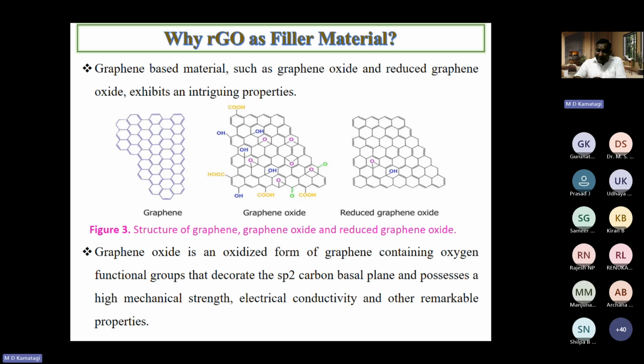The reduction of graphene oxide involves removing oxygen-containing functional groups such as the hydroxyl group OH, the epoxy group, the carbonyl group, that is CO, and the carboxyl group, that is COOH. These groups are introduced during the oxidation of graphite to create graphene oxide. Graphene oxide is highly hydrophilic and insulating. By reducing these oxygen functionalities, graphene oxide regains properties similar to graphene.